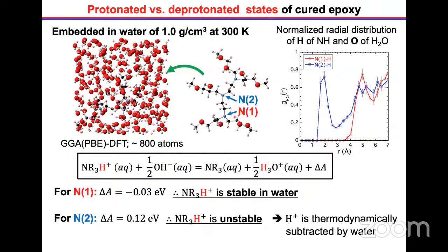Then what we did is that a slightly shortened cured epoxy molecule was inserted in the water molecular system. Then we calculated this data. In N1 and N2, the free energy is a little bit different. N1 is a negative value, N2 is positive. That means that this protonated state is stable in N1. In N2, the proton is subtracted by the water because, as this figure shows, in N2 cases, this is the distribution of the hydrogen of NH and O of H2O. Water molecules can come very close to this amine. So water molecules subtract the hydrogen ions.